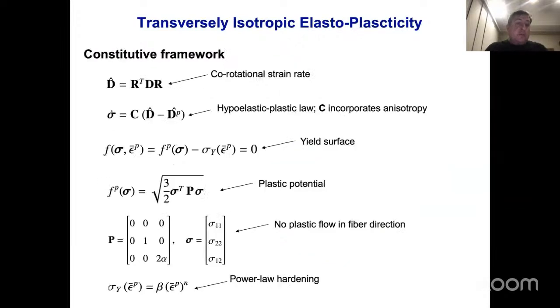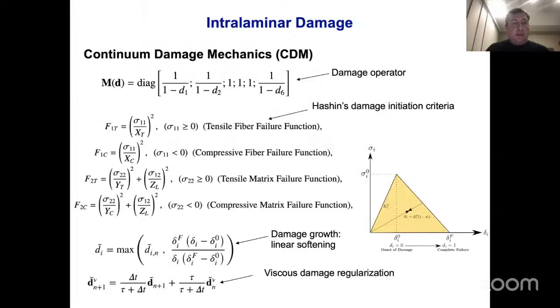And so now in this principal coordinate system, we define a corotational strain rate. We use the rate form of the stress equation. dP is the plastic strain in the corotational coordinates. Here's a definition of a yield surface. It uses a plastic potential that's expressed in this matrix format. P is the projection tensor, where you can clearly see that we're only taking into account stresses in the matrix direction and shears. So we're assuming that no plasticity occurs in the direction of the fiber, and we use power law hardening, which is again common for epoxy type materials. And on top of that, we're applying continuum damage mechanics.